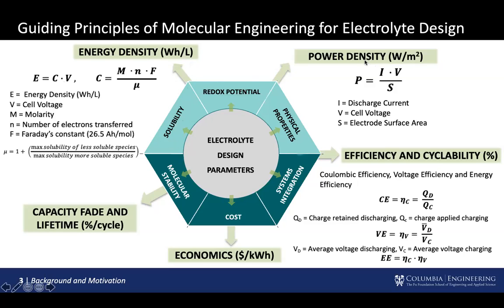So in the same way, if we look at power density, we see, again, V cell as a consideration, and we also see that this discharge current is related to the physical properties of the electrolyte, such as its viscosity and its conductivity and the kinetics of the redox reaction that's happening there. If we look at capacity fade, that's going to be given by the molecular stability of those redox active species. So again, we can see all these connections between top performance parameters and properties of the electrolyte.